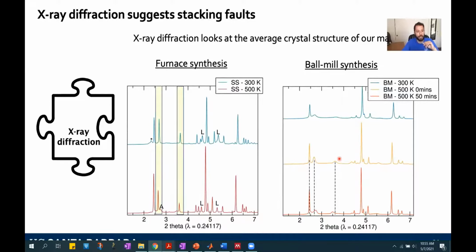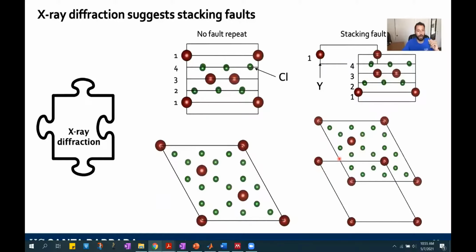Focus on these sets of peaks in the furnace synthesis. We can tell that they're pretty sharp on our furnace side, but as soon as we go to our ball mill synthesis, they become really flat and broad, and that's a sign of stacking faults. So we can try to create a model for this stacking fault, and on the left here, we have no faulting, and that means just 1, 2, 3, 4, and then 1 directly on top of that.